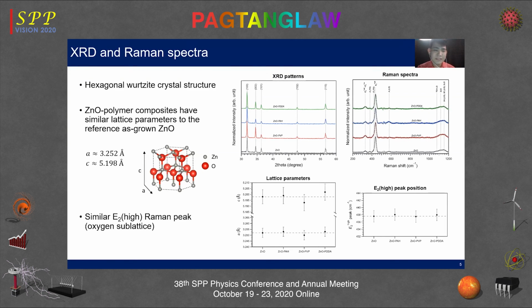For Raman spectra, the Raman phonon modes are also indexed with the hexagonal wurtzite crystal structure of ZnO with a similar characteristic E2 high Raman peak. And in terms of structural properties, the ZnO polymer composites are the same as the pure ZnO microrods.